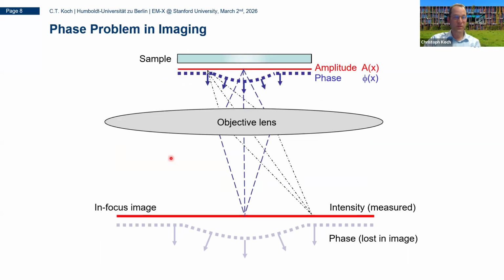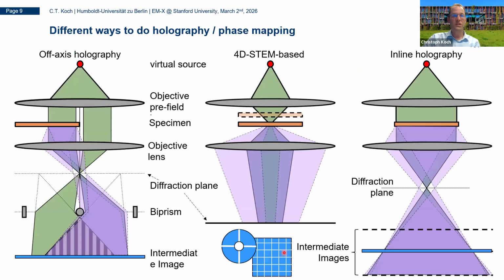The problem with modern microscopes that have aberration correctors is that you eliminate all the aberrations if you've really tuned them to minimize them. And then you can actually observe only the scattered intensity. And if you have a thin sample, which only has a phase shift like this, then you don't see anything. Actually, this phase shift is lost. And this has led to a number of techniques being developed.